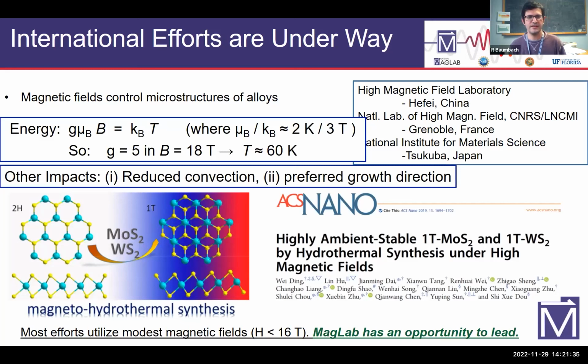Okay, but the story doesn't end there. Another place where this is important to consider is that if we consider the relative energy scales between a magnetic field and temperature, we kind of naively have this idea that a Kelvin is a Tesla. But that's only really true if we're not thinking about the G factor. So amongst lanthanide elements, where you can have a G factor, for example, as large as 5, then in a field of 18 Tesla, that energy scale gets to be more like 60 Kelvin. And if we're doing our growths between 500 and 1,000 degrees C, this starts to matter. It's a new axis that we can add to our phase diagrams where we might actually uncover new phases of